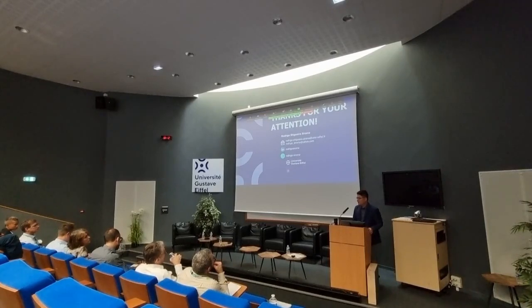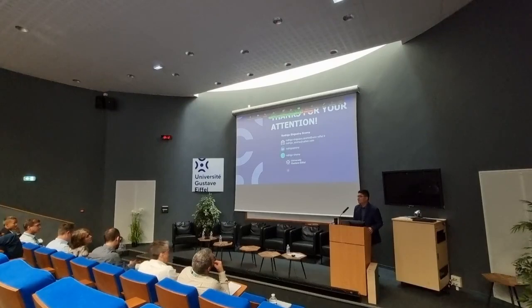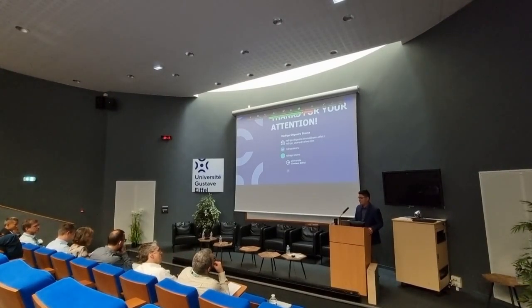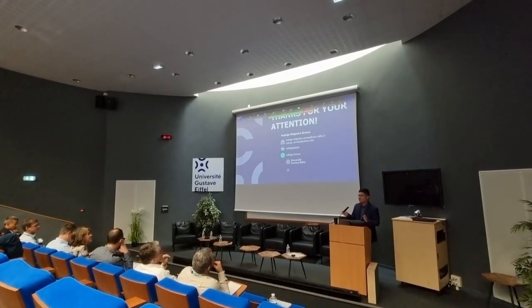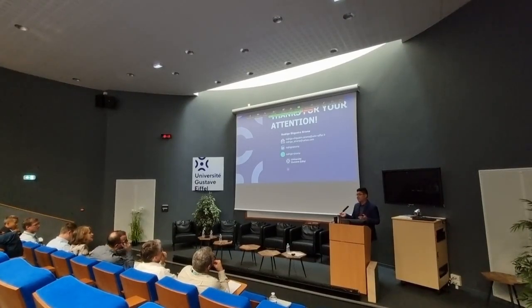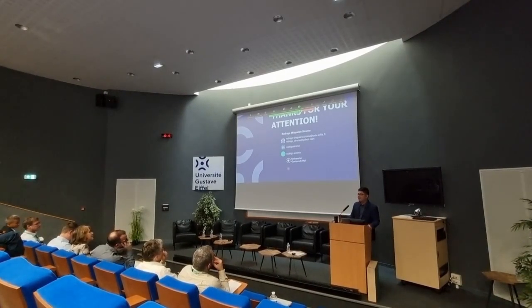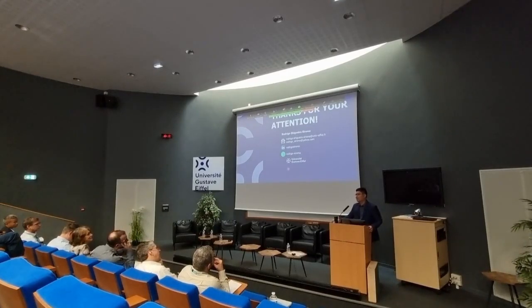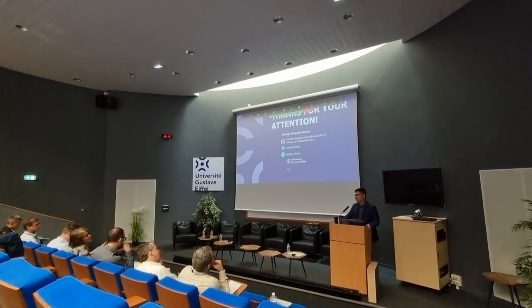Yes, you're right. Actually, it's just in chapter 4 that I present bitumen P, because this is the polymer modified bitumen, and the overwhelming part of my work was on unmodified bitumen. It was just based on the properties that we could observe, according to this aging indicator that is often used, it seems that bitumen P evolves slower than bitumen A in terms of its parameters. But yes, of course, it could have been investigated further.